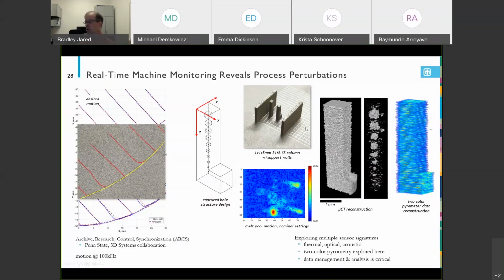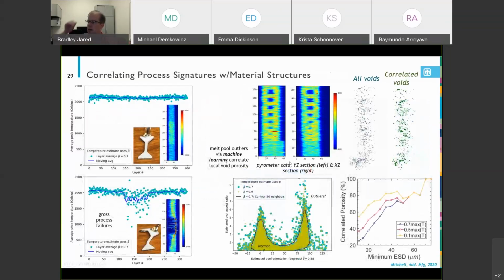But we did a bunch of CT data inspection of these parts, looked at the pyrometry data, and have done some things like machine learning with some clustering algorithms to show that we can find these outliers in these melt pools that correlate typically with spatter events. So basically, an upset where you have molten particles flying out of the melt pool. We start correlating these, and we can identify these large porosity voids in the structure, right? And so this gives us the ability to find porosity.